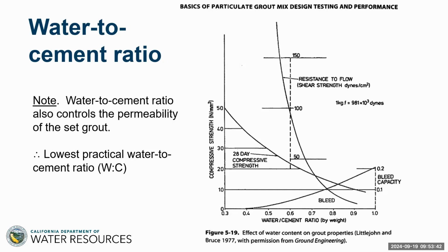So why are we tempted to go with high water cement ratios? And the answer is that upper curve, which is resistance to flow, i.e., if you like, thickness. So there's no question that you put more water into the mix, you increase the water cement ratio, it'll be easier to pump. But that's a false promise, because you're paying the penalty for strength and bleed. You might be able to pump it quicker, but you're going to get a pretty rotten product at the end of the day.